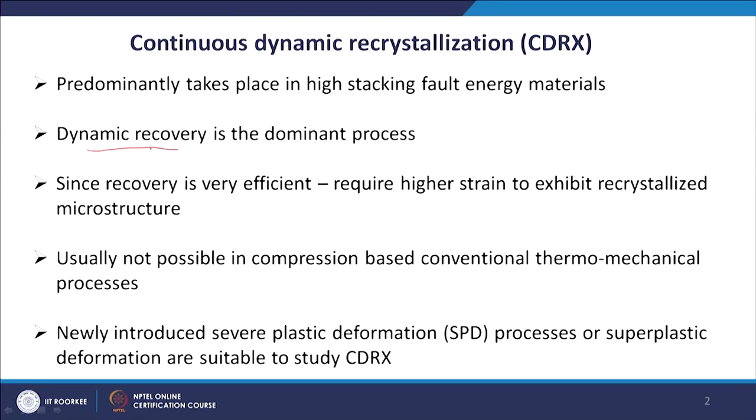Continuous dynamic recrystallization is actually very similar to a dynamic recovery type of process. In dynamic recovery, materials with high stacking fault energy predominantly restore their mechanical properties through dynamic recovery. In continuous dynamic recrystallization also, high stacking fault energy materials are the ones which are predominantly recrystallized through this process. Some people also refer to it as an extended recovery process — meaning if you take recovery to even larger strains, it will come as a recrystallization process.